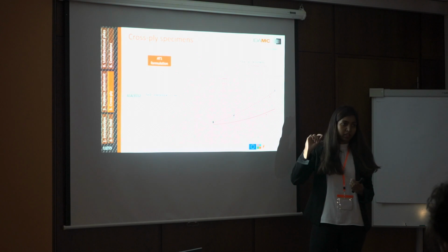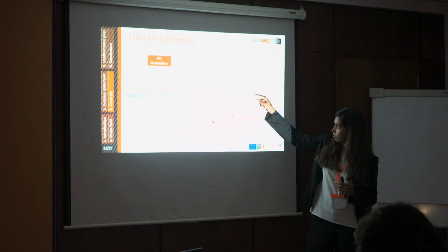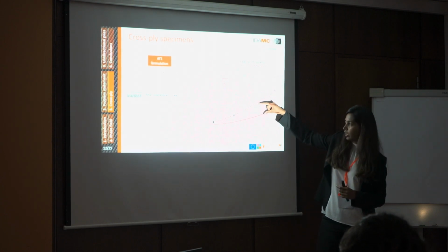Here the black curves represent the experimental and numerical failure moments, that is, the peak moments, and the other curves represent the damage initiation points. The dotted lines are from the numerical model, the circles are from experiments, and this is from the analytical calculation. If we look here, the black curves match perfectly well, whereas the red ones do not. That is for the first formulation.